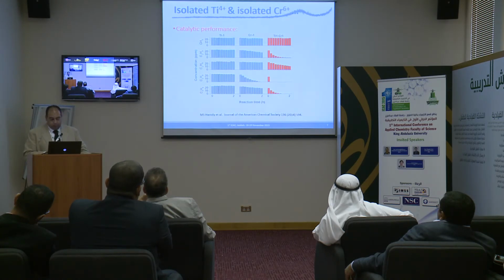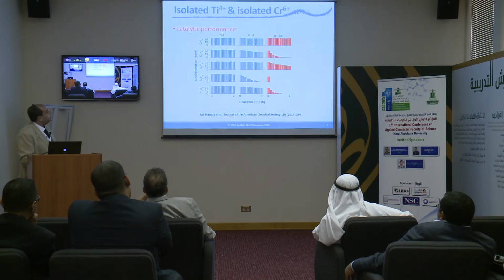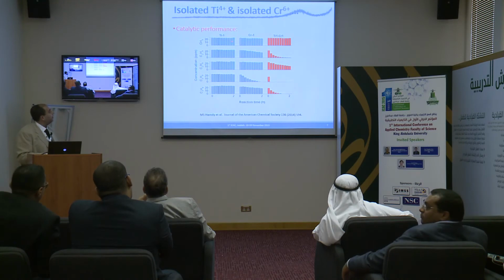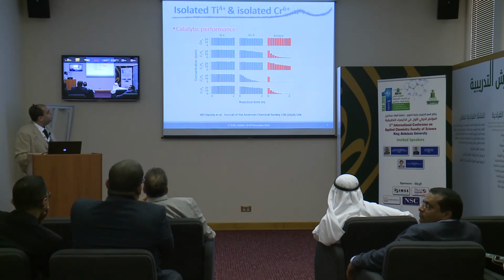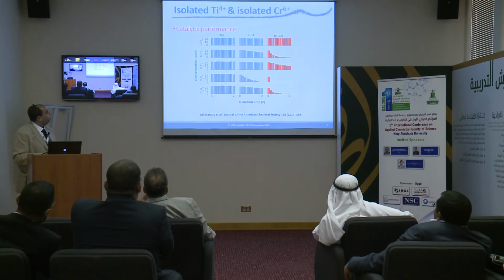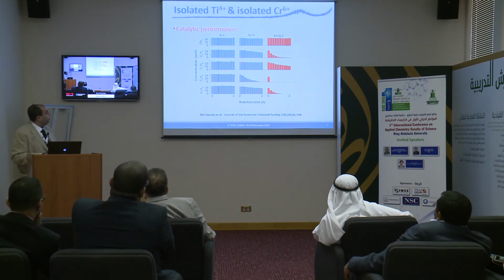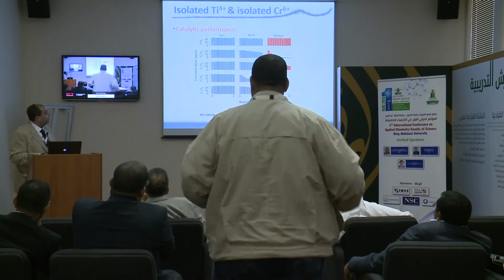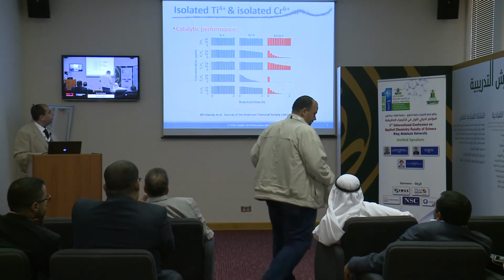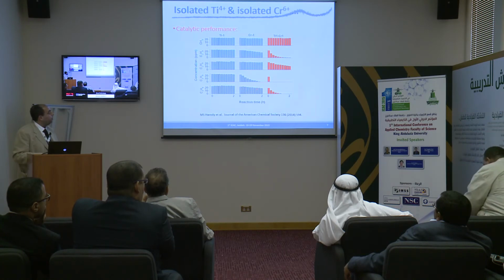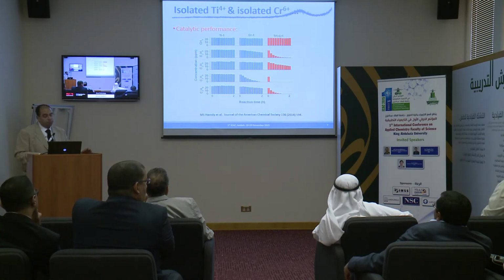So this is the catalytic performance of this material. Here, this is 1% titanium alone supported on silica matrix. You see almost there is no degradation at all of your gases. If you add now your chromium alone, methane is quite stable. You will start to get very small degradation in ethane, in ethylene. In propylene, yeah, you can find some degradation. And in propane, you can also get something like 15 to 20% degradation.